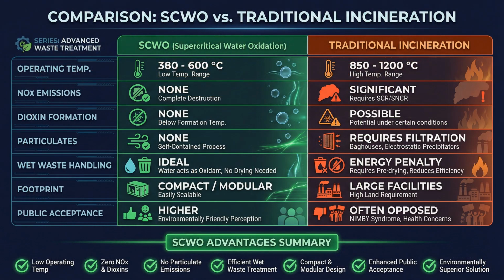SCWO offers significant advantages over traditional incineration for hazardous waste. Operating temperatures are 380 to 600 degrees Celsius versus 850 to 1200 for incinerators. Because temperatures stay below nitrogen oxide formation thresholds, SCWO produces no NOx emissions. Without a gas phase, no dioxins or furans can reform, a significant problem with incinerators. No particulate emissions result because everything stays in the liquid phase.